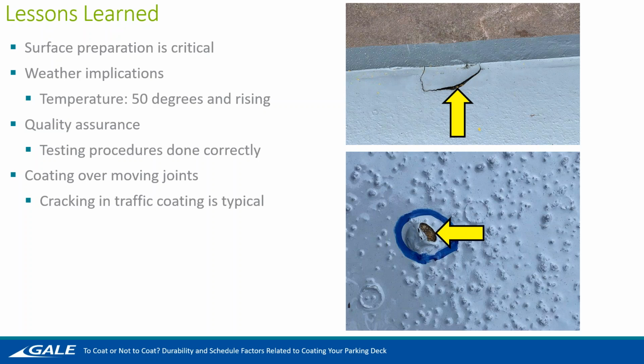Then quality assurance, so testing procedures are done correctly. It is important that a third-party person or a third-party company comes in at the end and does our pull tests. It's really critical that that's done correctly. It could look fine once it's cured, but shortly down the road, if each layer is not properly prepared or cleaned, or there's not enough grip between each layer, the pull test will bring that up. So instead of a year down the road, when everyone's gone and you now have a bubble in your concrete or it's failed in this location, the pull test can be a way to prevent that.